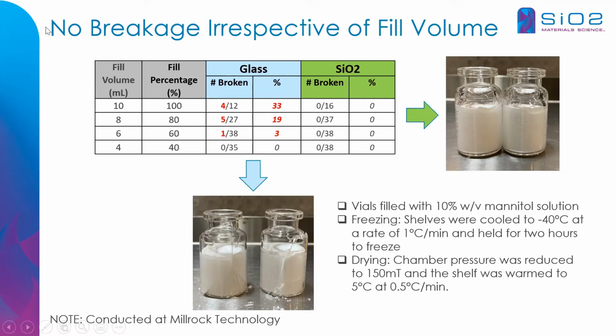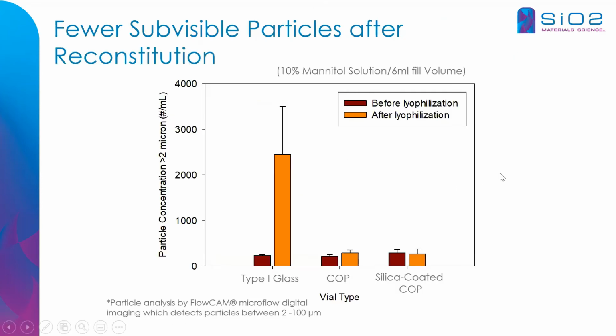And again, what you can see here is that you start seeing glass breakage when the fill volume exceeds 50%. At 40%, there's no breakage, and then as the fill volume increases up to 100%, you see more breakage. And that's not the case with SiO2, where you get a lot more flexibility with respect to fill volume.